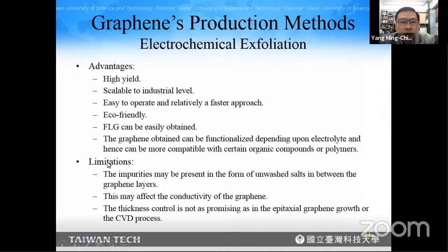compounds or polymers. The limitation of this process is that impurities may be present in the form of unwashed salt in between the graphene layers, because during the electrolytic reaction there are electrolytes in the solution, so that it may contaminate the graphene. This may affect the conductivity of the graphene, and the thickness control is not as promising as in epitaxial growth or the CVD process.